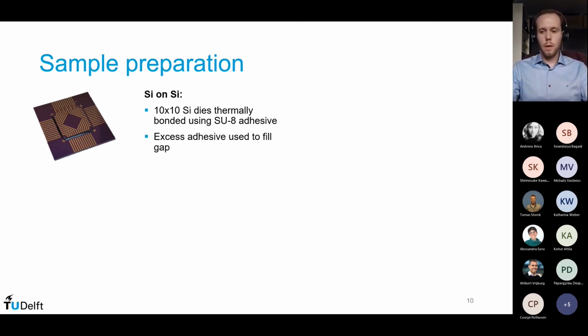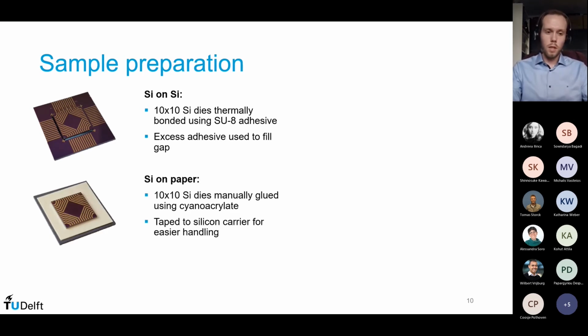And we have these gold electrodes, so we can also probe this fairly easily with our electronic probe station and measure the electrical performance. Proof that we can also do this on more fragile materials, which is one of the key benefits of this technology. We also put these chips on paper, so we can still probe them, but we can also prove that the connection to the paper can be made reliably and that the performance is good enough. Now, this was always taped to a silicon carrier to make sure that the sample is easy to handle and mount, because paper is still fragile by itself. But if you remove this, the sample will still be functional.